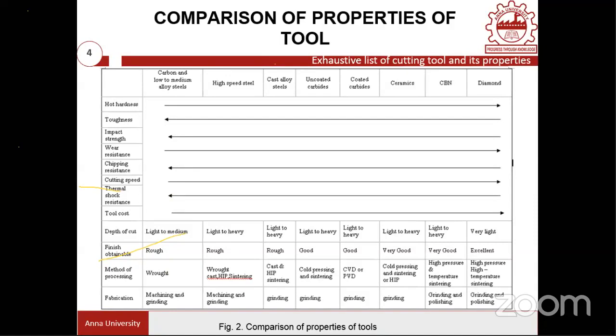So here I have a comparison of high-speed steel, carbide, and some of the ceramics, CBN and diamond. The hardness value keeps on increasing up the ladder from HSS to diamond. The CERMET has a medium hardness compared to diamond. Whereas for toughness, the diamond has very poor toughness, and the toughness of high-speed steel is really high. Similarly for impact strength, because a brittle material will have poor impact strength. Wear resistance will be very high because the hardness value is higher. As a result, the wear resistance is also higher for ceramics, CERMETS, CBN and diamond.